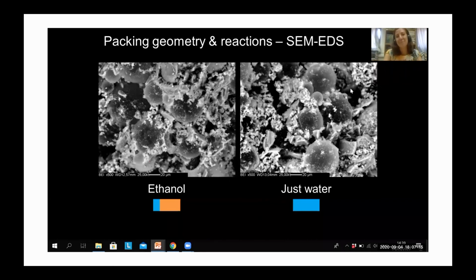So this is the typical grout just with water. With this kind of alternative suspension medium, of course, balanced, so there is the minimum water amount for the reactions to occur, but still the grout has acceptable properties, good performance characteristics and working properties, and high porosity. Still, all the chemical reactions are occurring, and indeed, they look very similar because the mineralogical phases formed